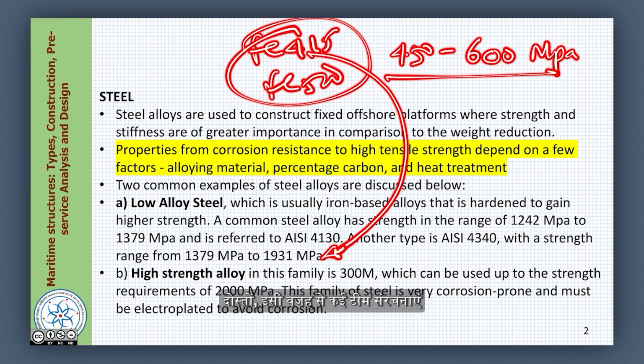Friends, it is because of this reason that maritime structures are sleek and elegant. At the same time, the weight reduction plays a very important role compared to its higher strength and corrosion resistance. When we talk about high strength alloy, it is a family of 300 M whose strength can exceed 2000 megapascal. It can cross about 2000 Newton per mm square. This family of steel has a very great disadvantage. It is very corrosion prone and must be electroplated to avoid corrosion. So, strength and corrosion do not go together.